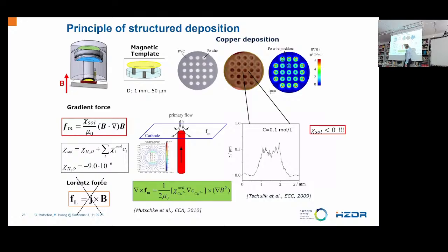And that gradient of the species concentration initially is directed vertically. You have a uniform deposition initially, but the magnetic element creates gradients in horizontal direction underneath the surface, which then feeds this cross product and creates a curl that sucks the fluid downward and leads to this enrichment and to the higher deposit there.